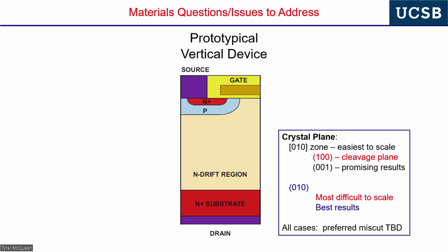Okay, in GaN, they were largely resolved because Shuji Nakamura started growing on all orientations of sapphire, and he found, not based on morphology or anything in microstructure, he used electron mobility as his metric, and he found the optimal miscut for sapphire. And then many subsequent studies showed he really had found the right miscut. Okay, but that's a lot of experiments. It's a lot of volume of material consumed and a lot of cost.